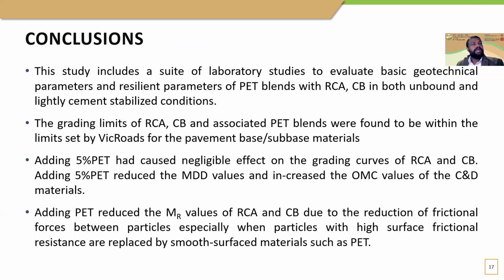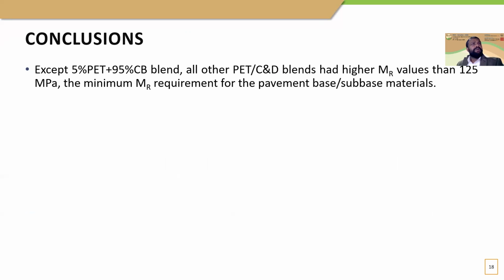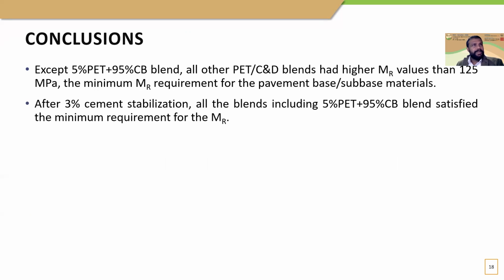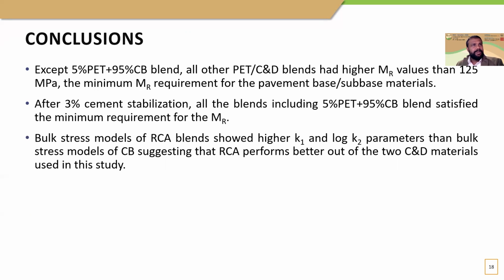Adding PET reduces the MR values of the RCA and CB due to the reduction of frictional forces between the particles, especially when particles with high surface frictional resistance are replaced by smooth surface materials such as PET. Except 5% PET, 95% CB blends, all the other blends had a higher MR value than 125 MPa, which is the minimum MR requirement for pavement base and sub-base materials. And after adding 3% stabilization, those blends will satisfy the requirement. And the K1 and log K2 parameters of the bulk stress models of RCA and CB suggest RCA performs better out of the two.